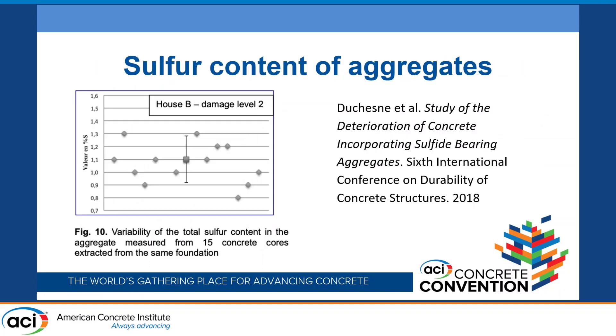Switching to sulfur: when talking about durability questions, results from Quebec, where they have some problems with sulfide-bearing aggregates — they did some post-mortem work with concrete cores from affected building foundations, used this technique to get the sulfur quantities, which helps them in their modeling of the investigation.